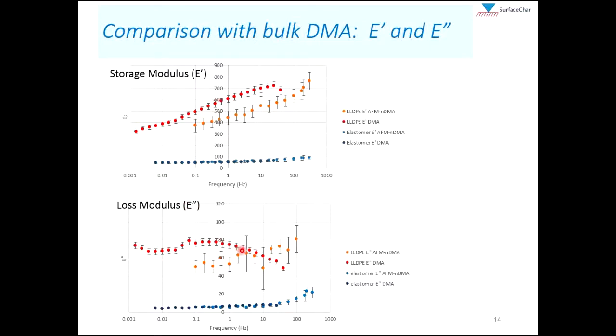And here we see similar trends for the loss modulus. Again, the elastomer is soft, so the tip is penetrating more into the sample, getting better signal. We get very nice agreement on the loss modulus, and a little bit low at low frequency for the polyethylene, the stiffer material, and a little bit on the high end for the higher frequencies.